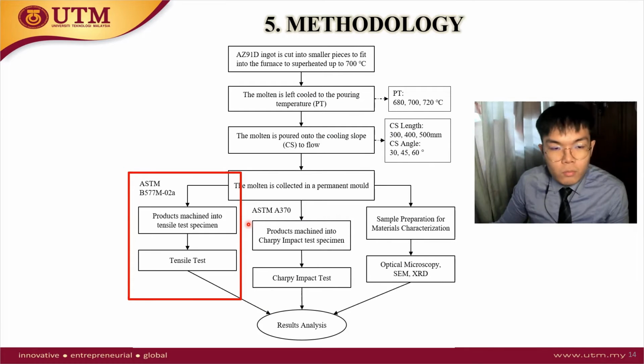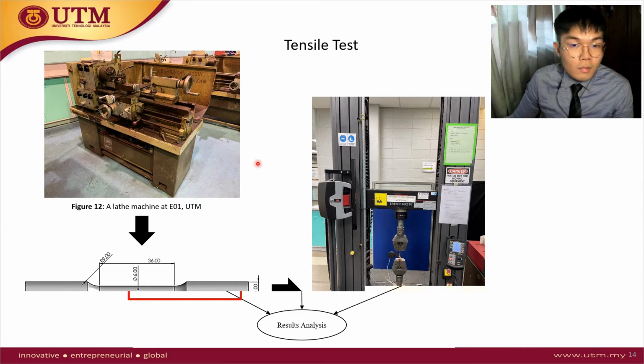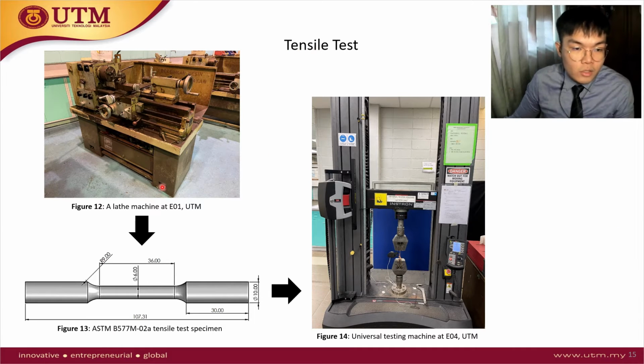After done casting, we perform mechanical testing. The first one is the tensile test. So we use a lathe machine at E01 to machine the specimen into the required geometry by ASTM standards, and then perform the tensile test using the universal testing machine at E04.